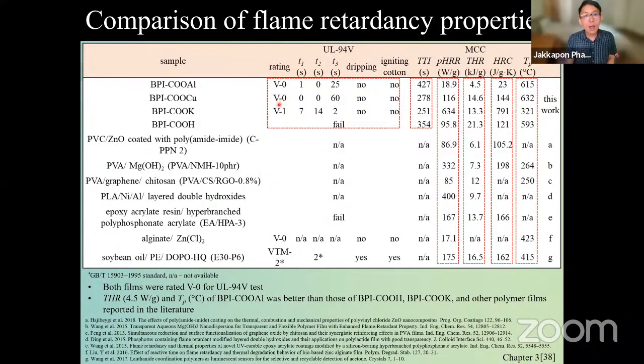Now, we also look at how it actually releases energy when it's burned, because if it releases so much energy when it burns and you are in the building, it's going to be very, very hot in the building, and that's not very good. It can kill you if it's getting too hot when it's burned. So you can see that the aluminum has a very low total energy release. We want the value to be as low as possible. The other studies are also quite low, at 6, 7, but for our aluminum we only have 4.5 total heat release, which is very, very low, which is quite good for the flame retardancy property.